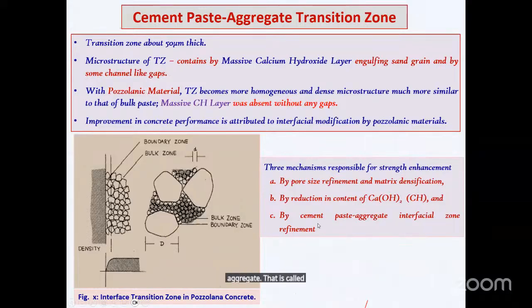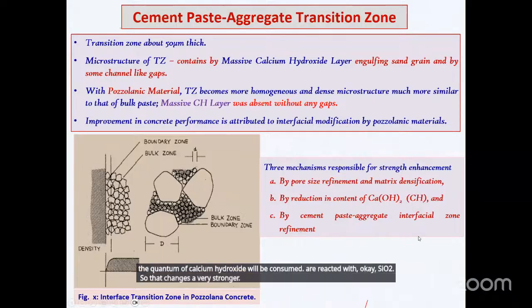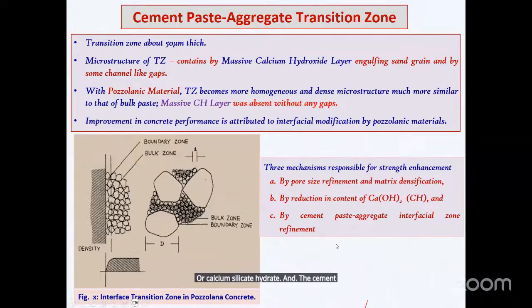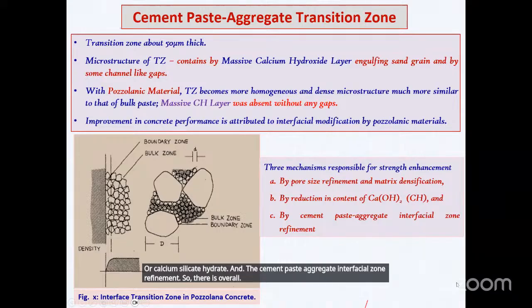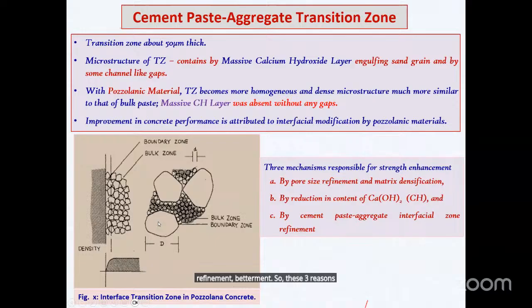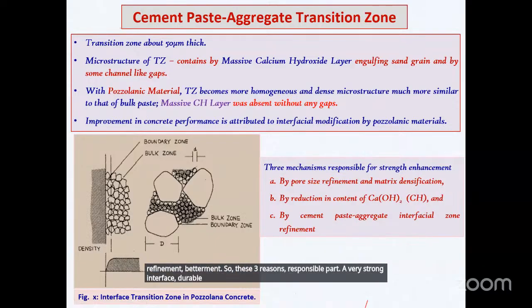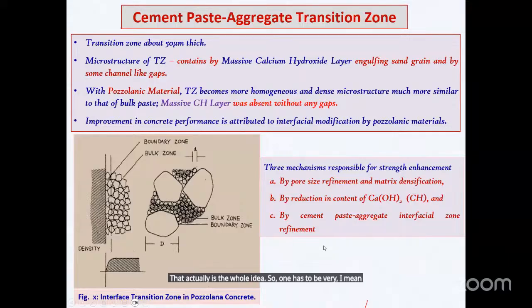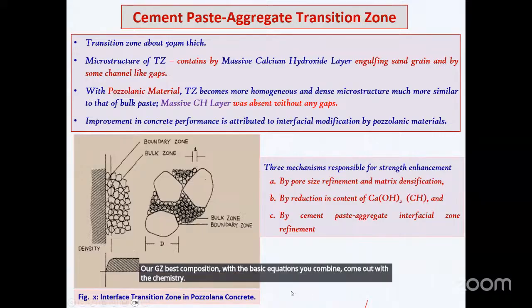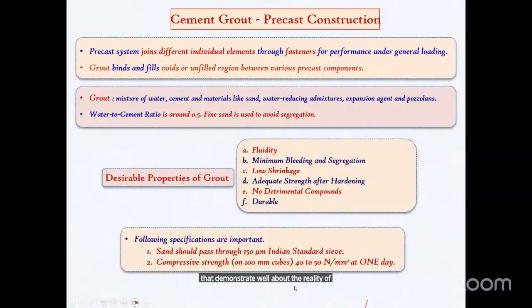That is called the interface. And also calcium hydroxide is being reacted with SiO2, so the quantum of calcium hydroxide will be consumed. That produces a very strong calcium silicate hydrate, and refinement of the cement paste-aggregate interfacial zone. So there is overall refinement, betterment. These three reasons are responsible for a very strong, durable, impervious interface. That is the whole idea. So one has to understand what exactly is happening. What is the fly ash chemical composition, silica fume composition, or GGBS composition? With the basic equations you combine, you come out with a chemistry that demonstrates well the reality of the reaction happening. That is one thing.